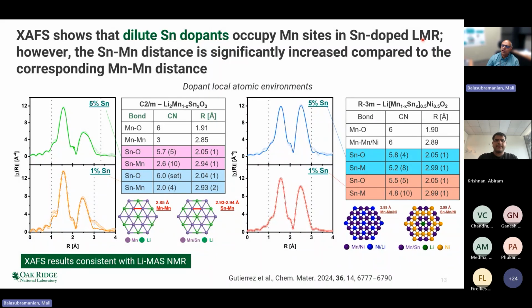So they clearly occupy the sites that we wanted them to occupy. However, the tin manganese distance is significantly increased when compared to the manganese manganese distance. So you can see that in pure Li2MnO3, the manganese manganese distance is around 2.85 angstroms. But when you put tin into manganese type sites in Li2MnO3, the tin manganese distance increases by about 0.1 angstroms.